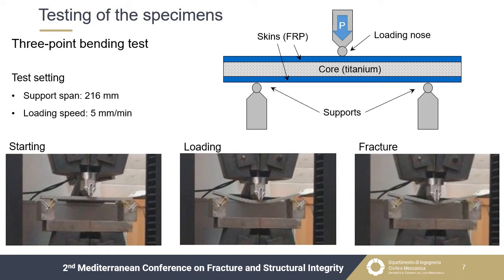behavior analysis. The test scheme consisted in the typical 3-point bending flexure. The specimen was placed on two supports and it was loaded in the center by a loading nose. The span length was chosen equal to 216 mm, while the loading speed to 5 mm per minute. After the starting of the test, each specimen was loaded until the fracture.